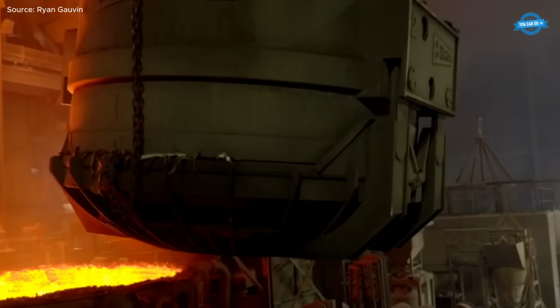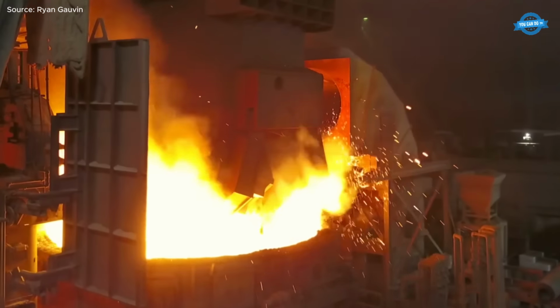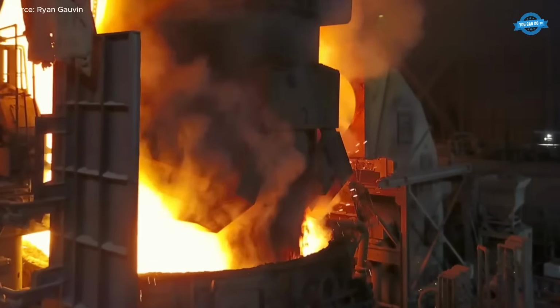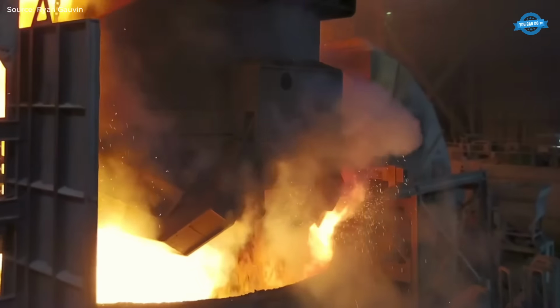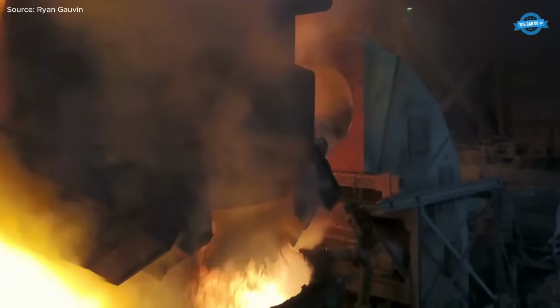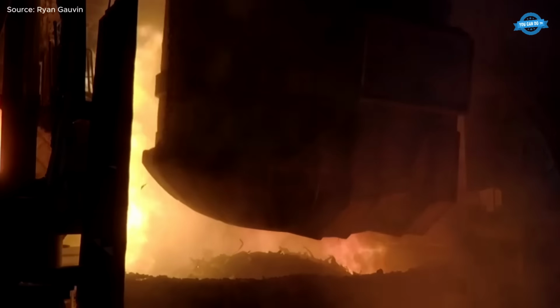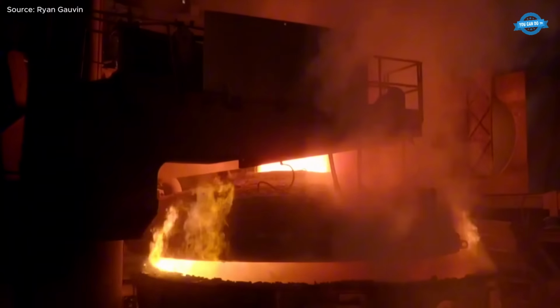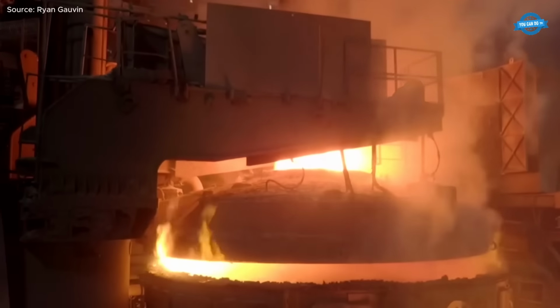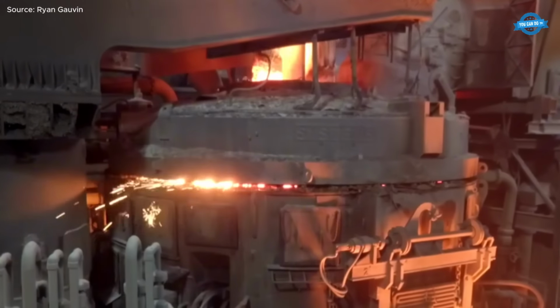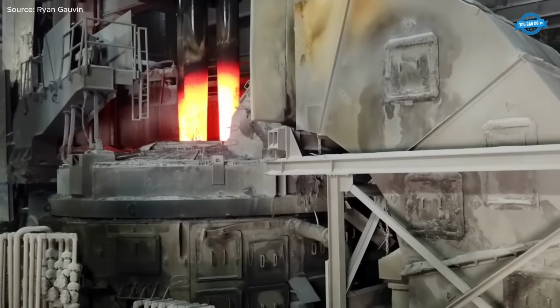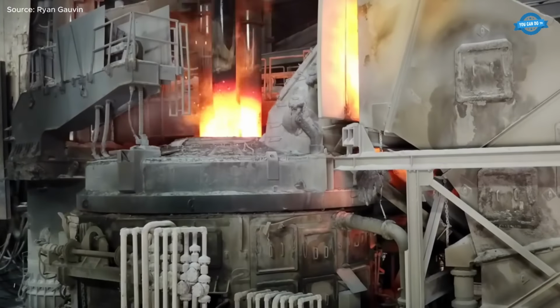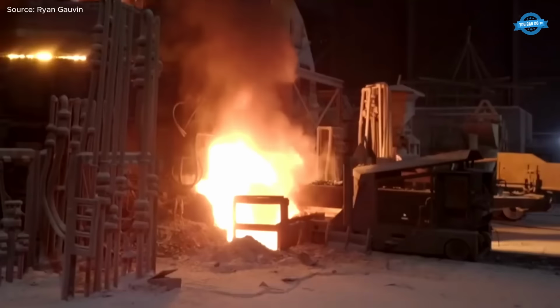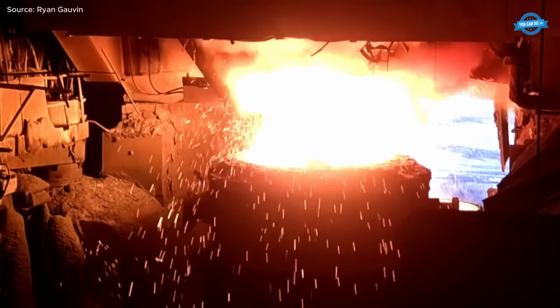Steel production at Nucor follows a fully integrated high-efficiency route built around the electric arc furnace. The cycle starts in the scrapyard, where recycled steel is sorted and prepared before being charged into the furnace. Powerful electrical arcs generate extreme temperatures, rapidly melting the scrap. During refining, slag forms to absorb impurities and is removed before the clean molten steel is tapped into a ladle.